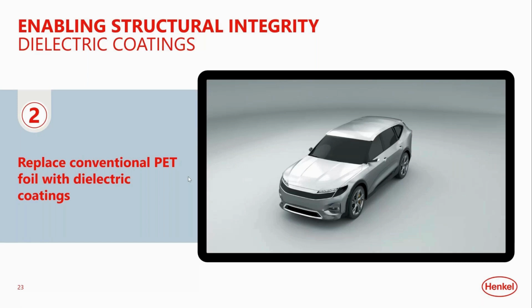So if the PET sticks to the cell at say 2 megapascals and my thermally conductive adhesive is at 10, I'm still always going to have that limit of 2 as the weakest interfacial layer. So we need to find a different method to ensure that electrical isolation for safety reasons, but create a much higher adhesion to either the cell or cold plate. Then we can really maximize the strength or benefits of the thermally conductive adhesives that we previously discussed.